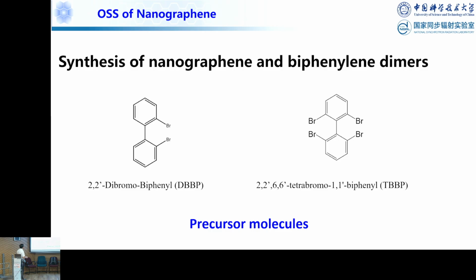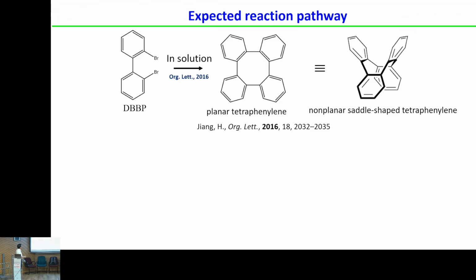First, we use these dibromo biphenyl precursors, and then here is tetrabromo. Because of this precursor, you draw the solution like this, but these single bonds, the molecular precursor can rotate. So at the beginning, we want to see whether it's possible to form graphene nanoribbons on the surface. In solution-based chemistry, you can see first for the tetraphenylene, planar this and equal this, so the non-planar, saddle shaped. So this is solution-based.